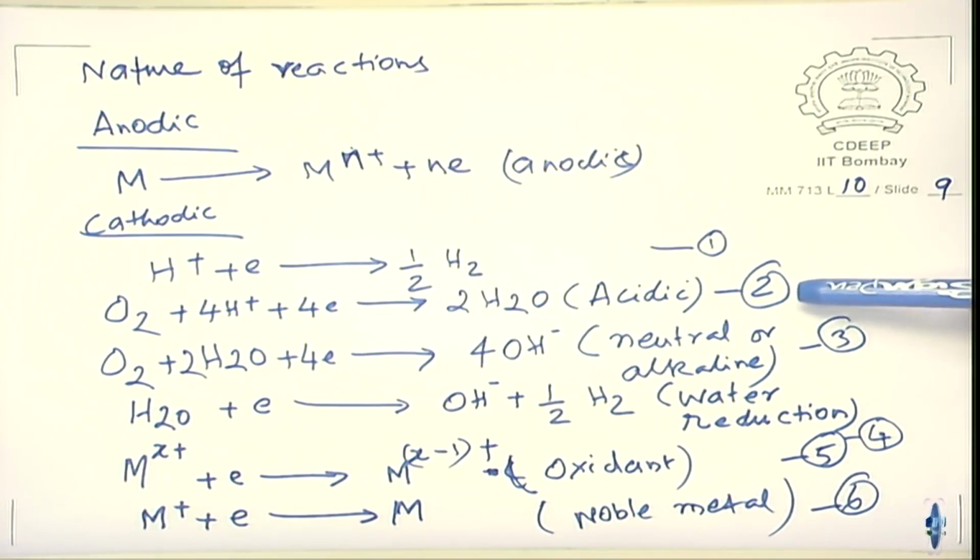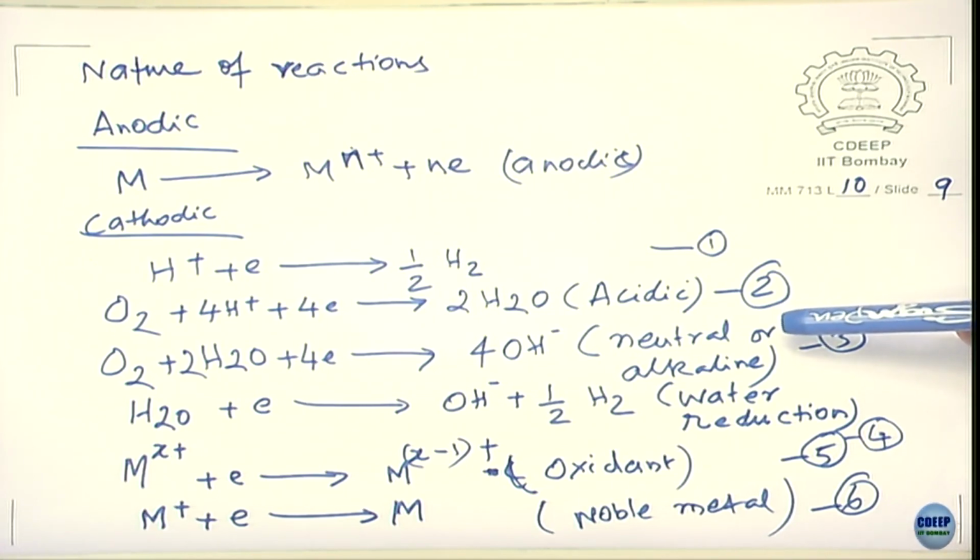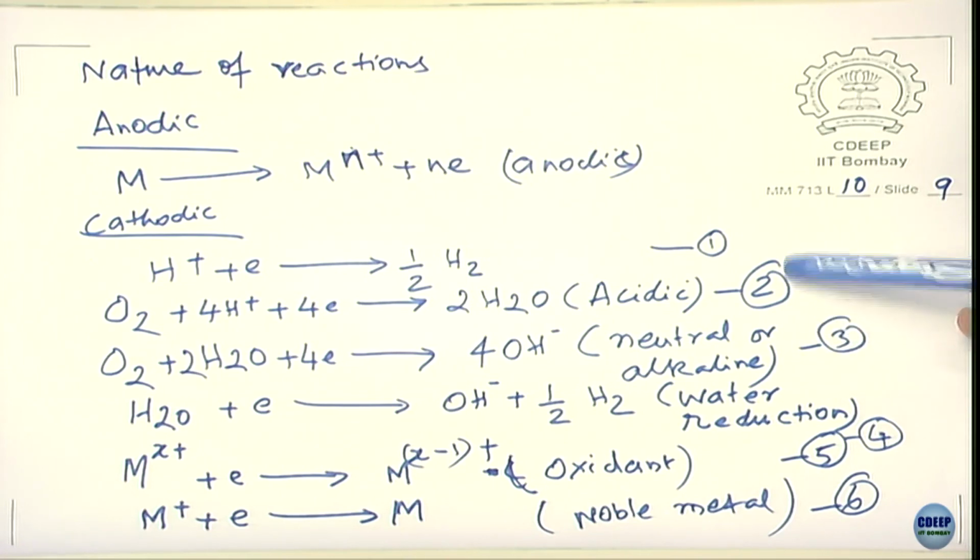I say number 2 is not a problem. I say number 2 is better. Can you defend me? Actually, passivity, right? Because the oxygen present in the stainless steel tank will passivate it. The same oxygen present in the carbon steel tank will be harmful to you, actually. So you need to try to understand this, unless you get a comprehensive idea, you can't analyze industrial problems. But it is very simple, you just apply the principles. However complex it is, they start unraveling one after another, but you need to go in this direction.